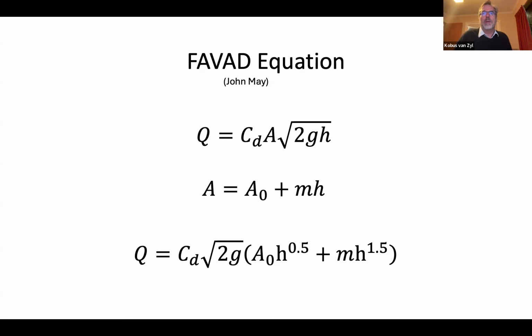But it also applies to a network or a DMA with many leaks. And so if you apply it to a DMA instead of the N1, you can get the total initial area of all the leaks and the total head area slope of all the leaks, which I think we should be using more because it's a physical value linked to it, and they're constant.